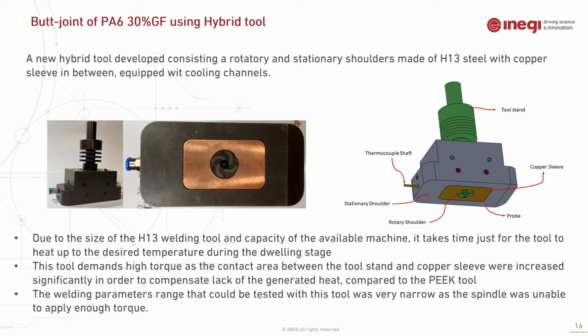And the stationary shoulder around would forge the plasticized material inside the weld pit, and the probe would stir the plasticized material under an axial force. However, due to the size of the H13 welding tool and capacity of the available machine, it takes time just for the tool to heat up to the desired temperature during the dwelling stage. So in some cases, additional heat source was needed.